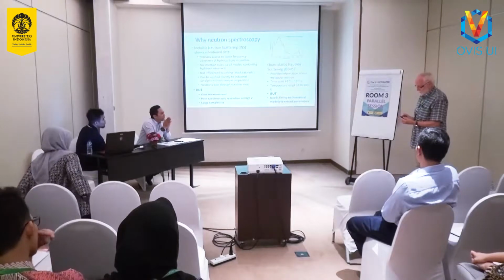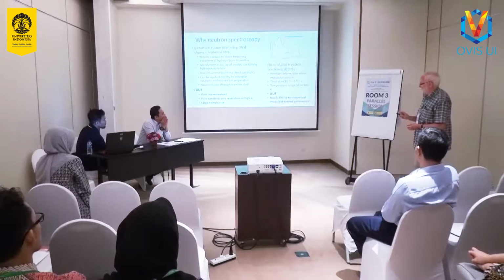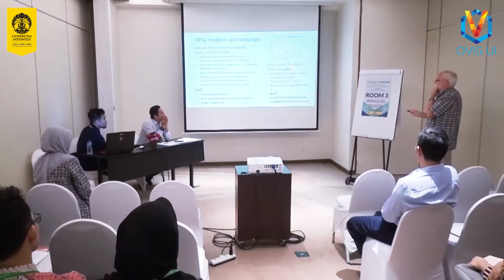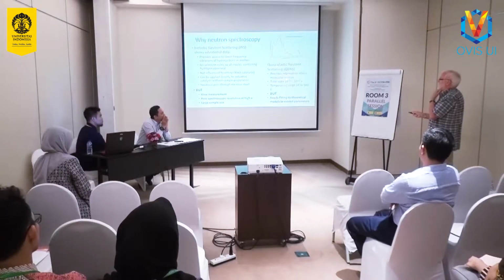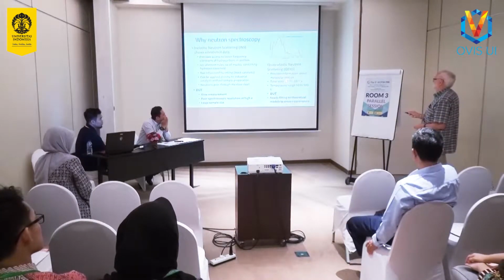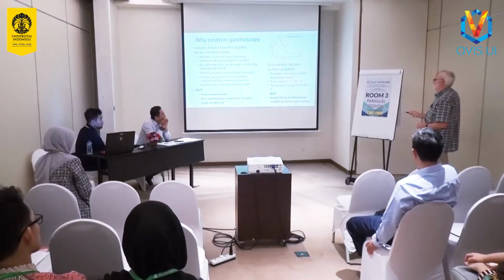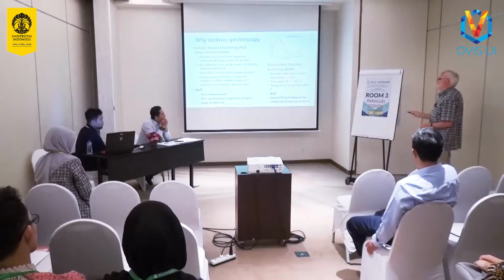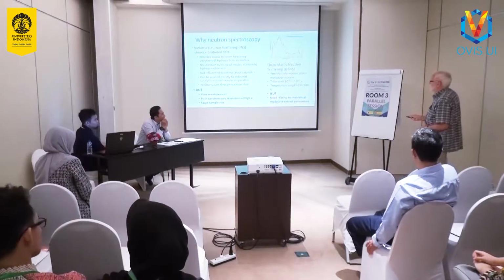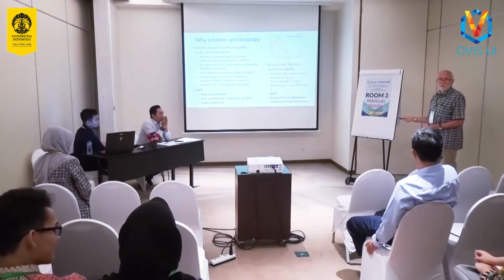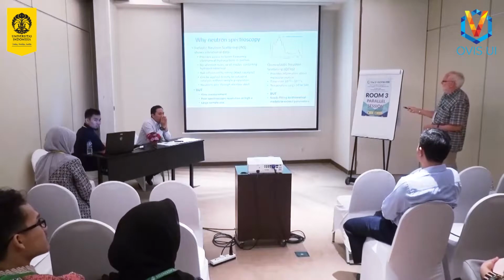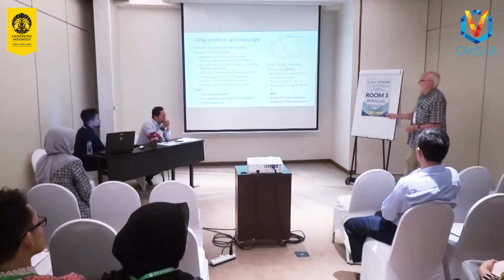So that's inelastic neutron scattering, giving us vibrational spectra. A related technique, which we tend to do at the same time, although not on the same spectrometers, I must say, it's a different instrument, is quasi-elastic neutron scattering, which is called QENS. And this technique gives us information not about structure, but about motion. The molecule, particularly in a porous catalyst like a zeolite, how the molecules are moving. If they're moving on a time scale in the picosecond range, then we can get information about the nature of that motion and how fast they're moving from the QENS experiment. I'll show you some examples. But to extract the information, we've got to fit to theoretical models. So it's quite a tricky procedure sometimes to fit the data to a theoretical model. But in principle, QENS gives us information about motion. INS gives us information about the structure.